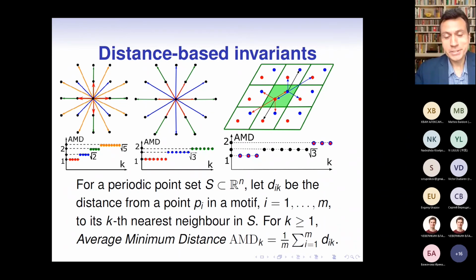And indeed, distances were mentioned in several past talks as good invariants of periodic structures. So that's a formal definition of the average minimum distance. We start from a periodic point set. And for every point p_i, we look at distances to its neighbors. First neighbor, second neighbor, and so on. So in the first picture, you see the square lattice. So the first neighbor of the origin has distance 1, and similarly, we have actually 4 neighbors at distance 1. Then we have 4 neighbors, diagonal points at distance √2, 4 neighbors at distance 2, and so on. For the hexagonal lattice, these distances are similarly increasing, but differently.